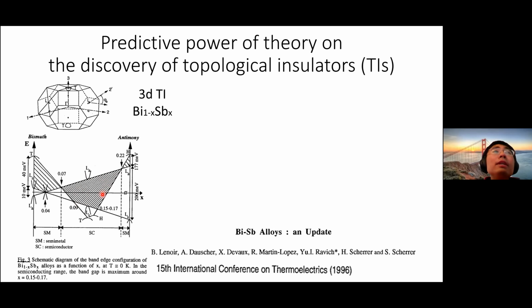The idea is based on a concept known as band inversion. In the case of topological insulators, when two bands with different parity, for example one band odd under inversion and the other even under inversion, cross at certain high symmetry points, for example at the gamma point or at the T point, which is also a time-reversal invariant momentum.